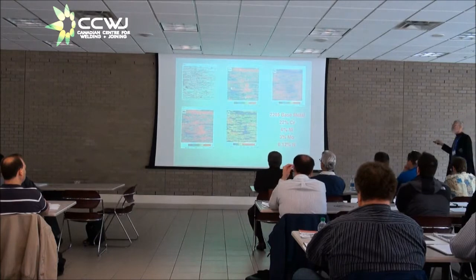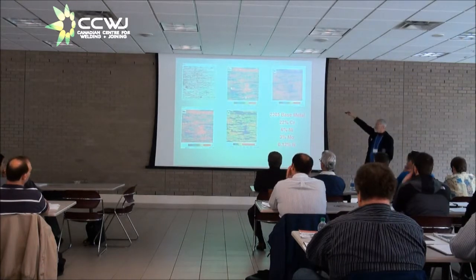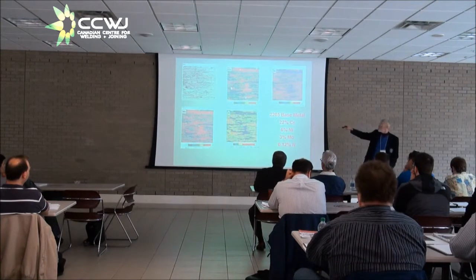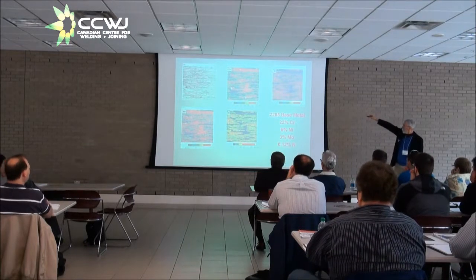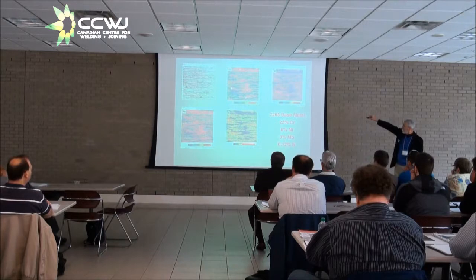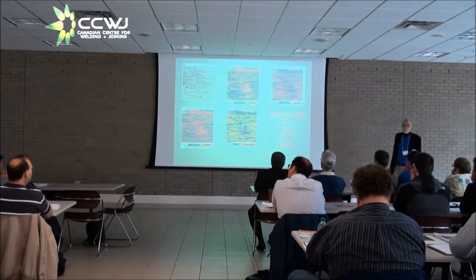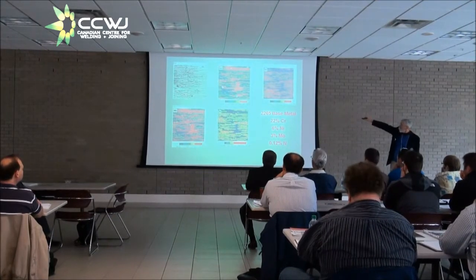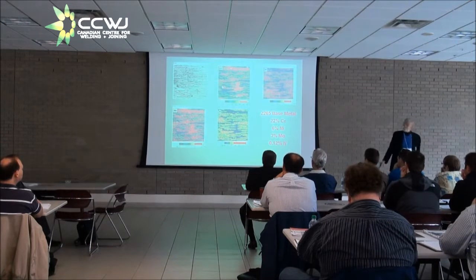And then what they did was use an electron microprobe to look at the distribution of the alloying elements in that wrought material. And each of the maps is color-coded so that you can see where the high concentration of an element is and where the low concentration is. So if you look at the ferrite area here, and you look at the chromium map that corresponds to it, you see the red color in the ferrite. And that corresponds to 25% chromium. The alloy only contains 22%. Conversely, if you look through the austenite area, which is blue here, that corresponds to 20% chromium. So there's a partitioning. Chromium promotes ferrite, so it segregates to the ferrite under equilibrium conditions.